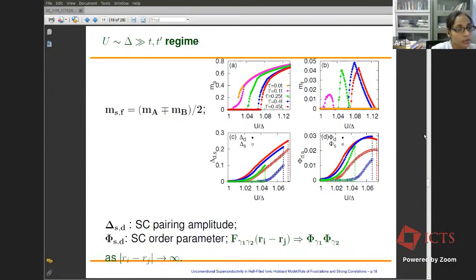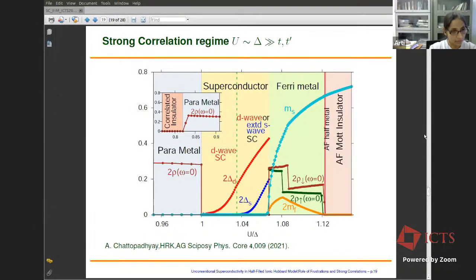Now, one point to emphasize here is that although the extended S wave superconductivity turns on at a much larger value of T prime, once it turns on, we have both the D wave and the extended S wave as viable solutions with very close ground state energies. So both of them coexist in certain parameter regions. This is the phase diagram for a fixed strength of the second neighbor hopping. Once the second neighbor hopping is sufficiently large such that the system can sustain superconductivity by frustrating the magnetic order, this is the phase diagram you get.